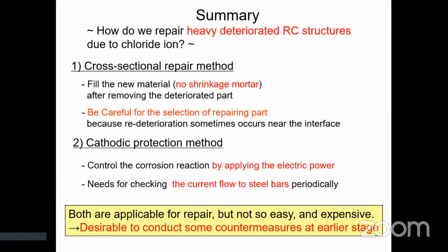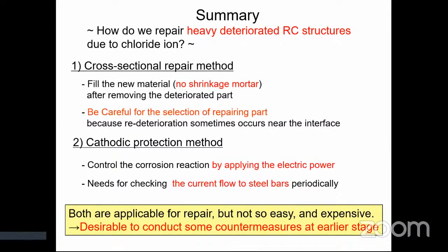This is the summary of this chapter. One repair method is the cross-sectional repair method. This method is conducted by filling new material, such as non-shrinkage mortar, after removing the deteriorated part. However, be careful in the selection of the repairing part because re-deterioration sometimes occurs near the interface. Another one is cathodic protection. This method can control the corrosion reaction by applying electric power. However, we have to check the current flow to the steel bar periodically. Both methods are applicable for repair works, but not so easy and expensive. It is better to conduct some countermeasures at an earlier stage with slight deterioration.